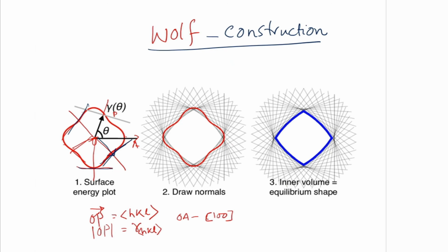So first and foremost is this aspect. Once you do that, you can get the equilibrium shapes, the shapes which will have the minimum energy. Remember, the condition being used in doing that is that you are minimizing the summation A_i gamma_i, where A is the surface area and gamma is the specific surface energy. So the total surface energy of the system is minimized the moment you do this construction. This can be mathematically proved, even by construction. But let us not get into all these difficulties. Just try to understand what the Wulff construction is, and how it can give you such an important equilibrium shape of a crystal.